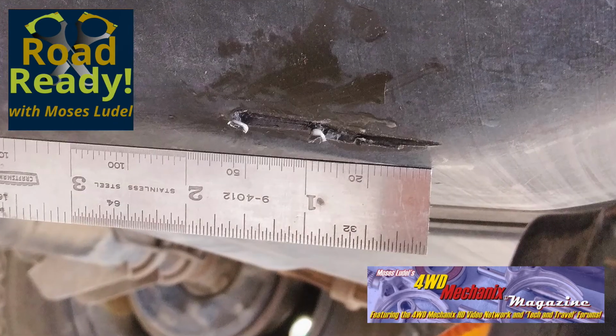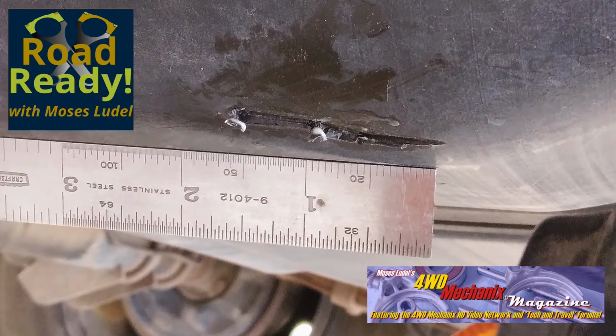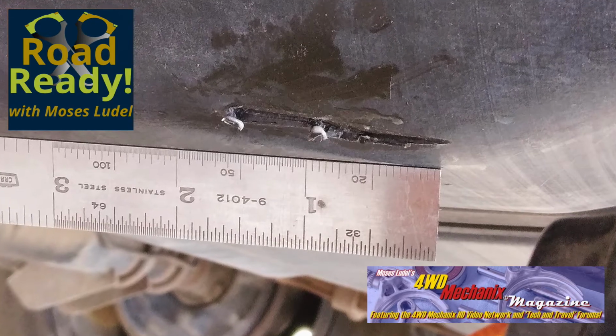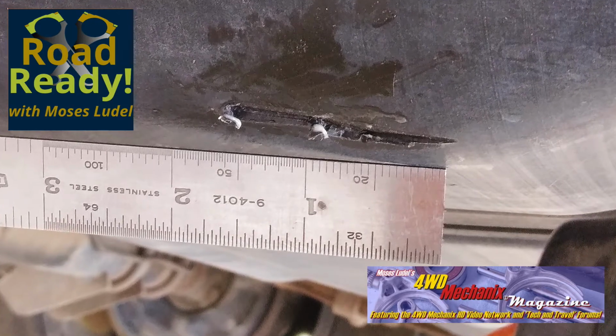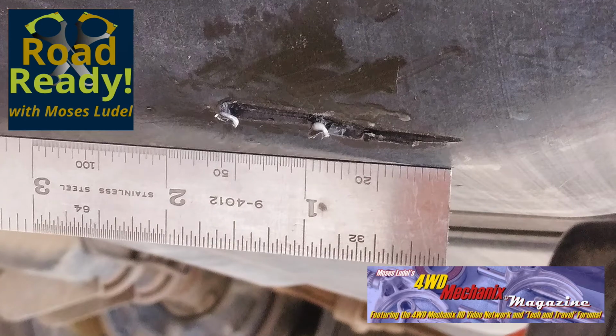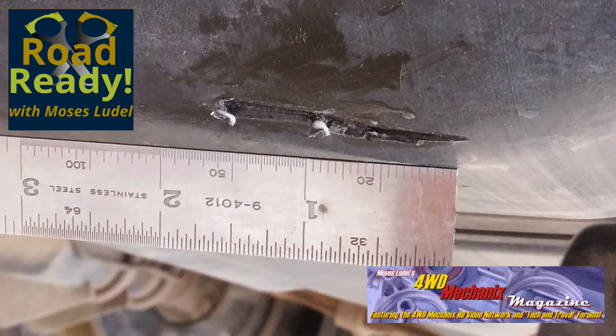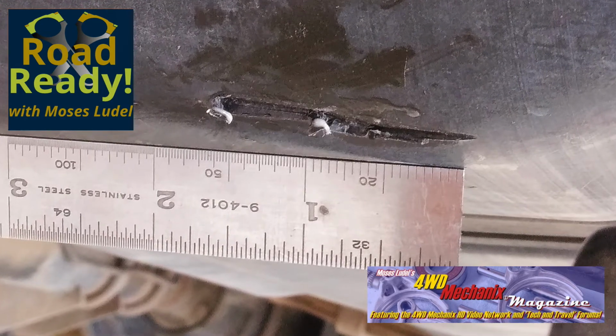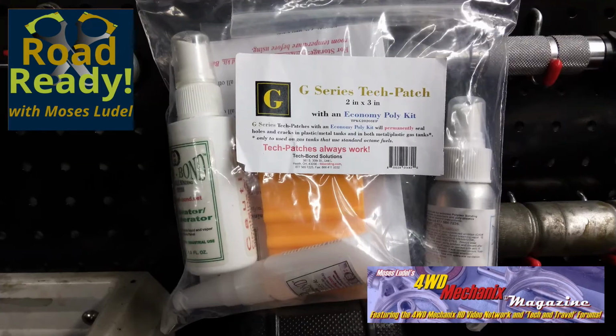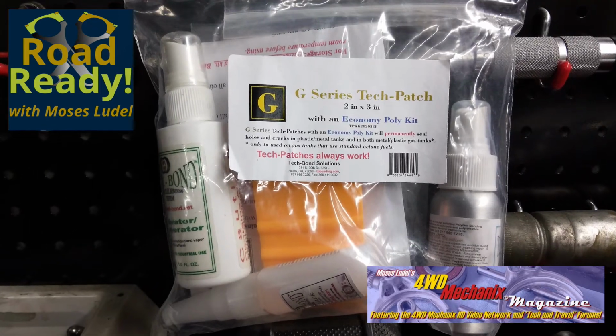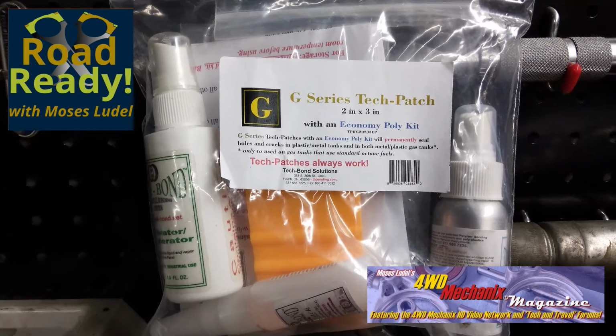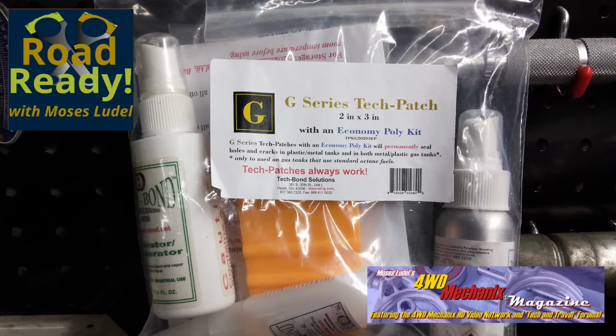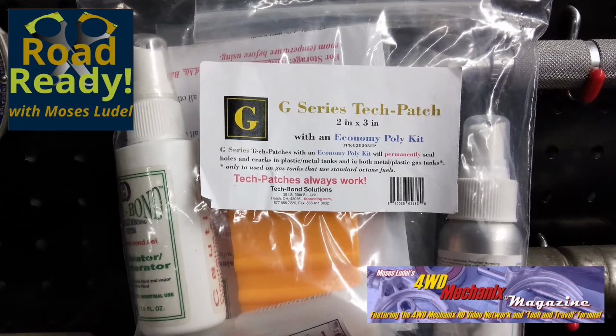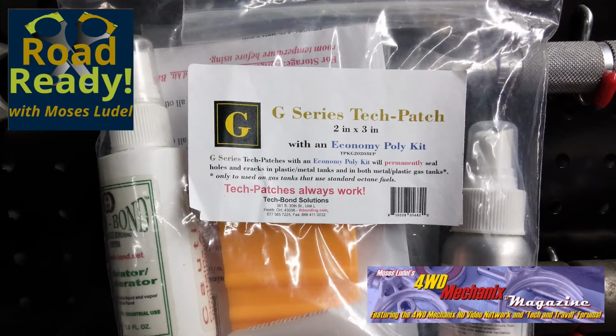The tank material was very thin at the scrape, but after a month showed only a slight sign of fuel permeation at the damaged area. There was no visible leaking or wetness. This was still not a full crack or puncture, but could quickly become one. According to Tech-Bond Solutions, the polymer bonding process repairs holes, full cracks, and more severe damage than our tank. The dry condition of the scrape made a tank in position repair possible.